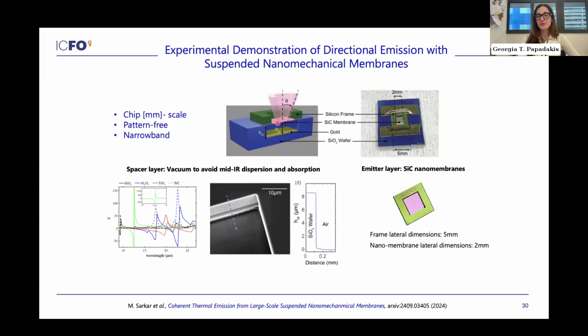So we built the Salisbury screen, which was not easy. And the reason why it was not easy is because you have to build a dielectric spacer. And in the mid-IR, a dielectric spacer in the order of the wavelength means that we have to have a dielectric layer that is on the order of 10 microns or so. And that's very difficult to get because of buckling and island formation.